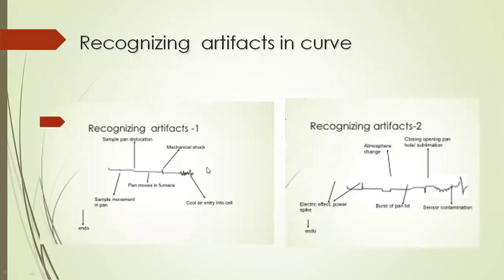Again, like in the case of TGA, you should be able to identify the artifacts in DSC also. This is not the TGA. This is the sample pan dislocation. This is the mechanical shock, not your sample behavior. This is the cool gas entered into your cell. This movement is your sample movement in the pan. This is not a thermal event. This is the electric effect, power fluctuation.